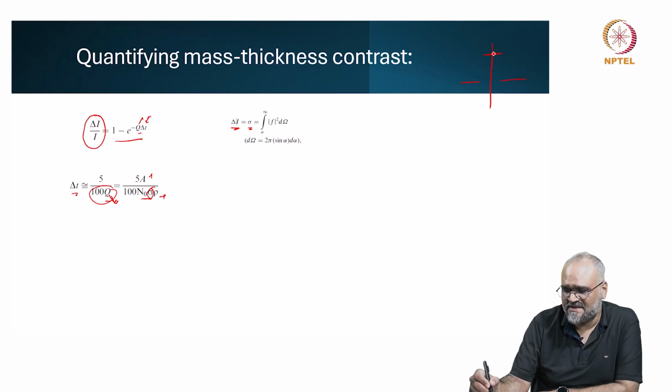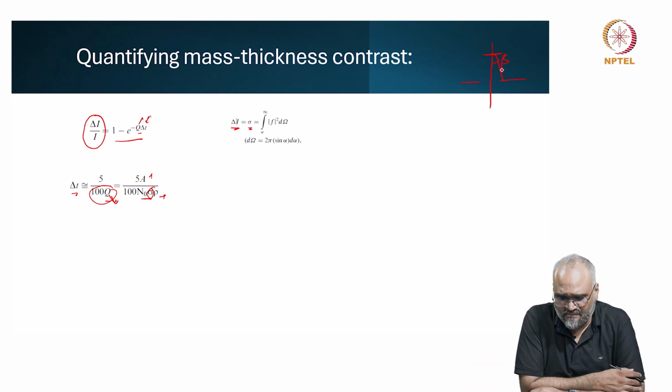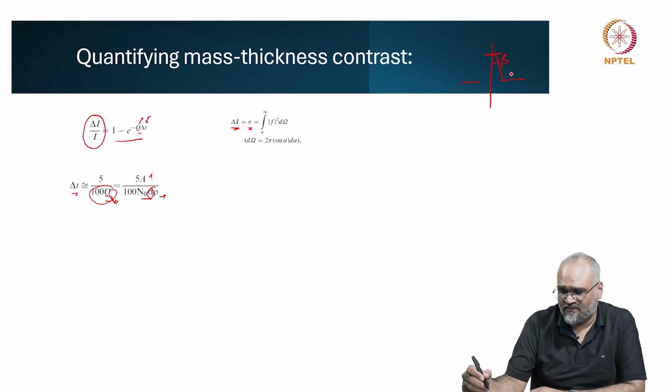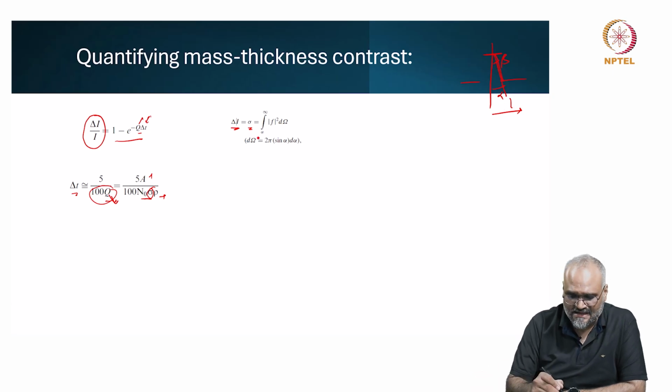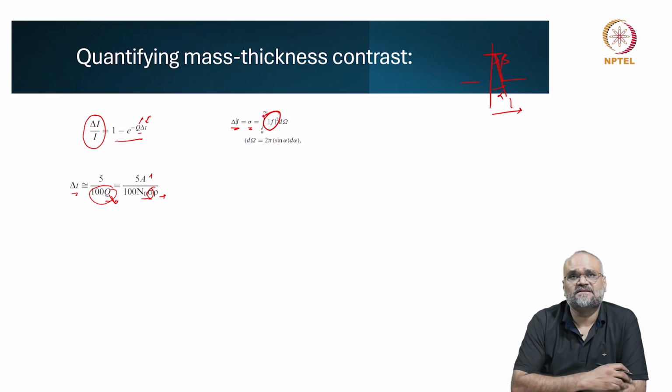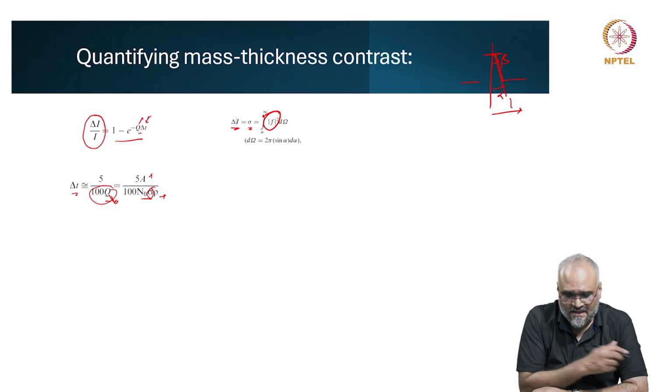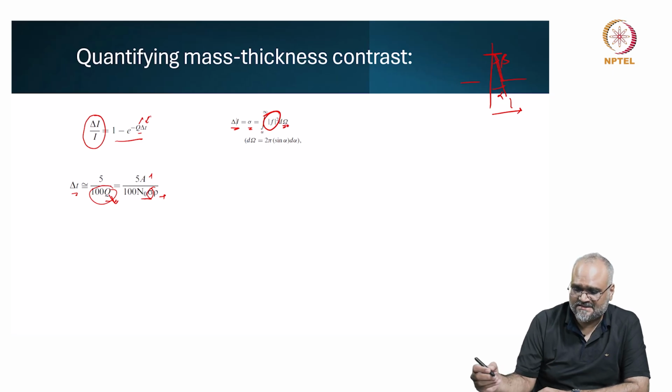So, if here is my specimen and I am recording the intensity values within a region which is scattering from an angle beta like this, or if I do not have any aperture as well, from the small deviation that is caused as a consequence of scattering, say alpha, I can integrate the intensity of the forward scattered electrons from this angle alpha to infinity, which is a function of the atomic scattering factor, and this omega is from the